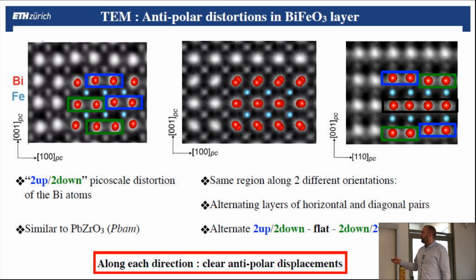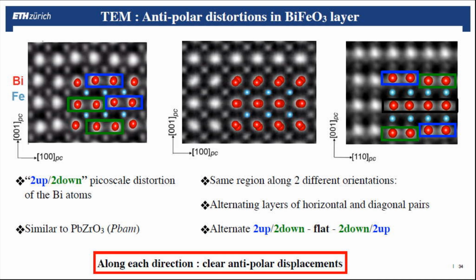So these are STM images, sorry for the S, which allow you to see the positions of your atoms. So imagine that you grow your crystal like this, and what they do is that they observe the alignment of atoms in that direction, for example. So the material grows in that direction, and here you are seeing a projection of everything that is behind what you see here. And what you can see here is in bright white the bismuth atoms, and here you might be able to distinguish the iron atoms, and you don't see the oxygen because they are too small. So that's what they observed.